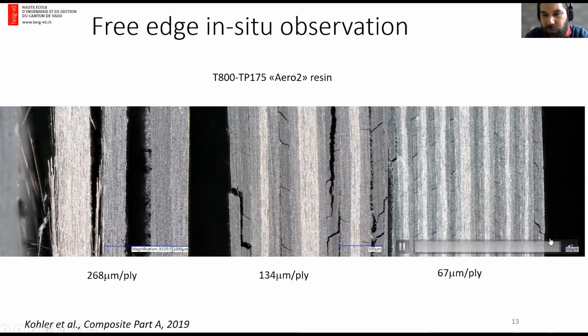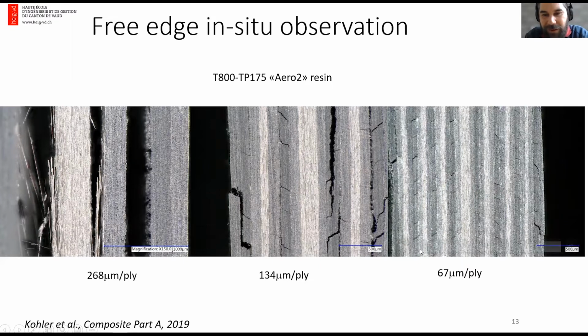And all these transverse cracks, at some point, they might propagate in delamination, but we couldn't observe it. We have an explosive fracture at the end of the test. So right after this point, everything explodes. And as you can see, there's no significant delamination in this laminate. So that's a very visual way of seeing what is the effect of reducing the ply thickness.